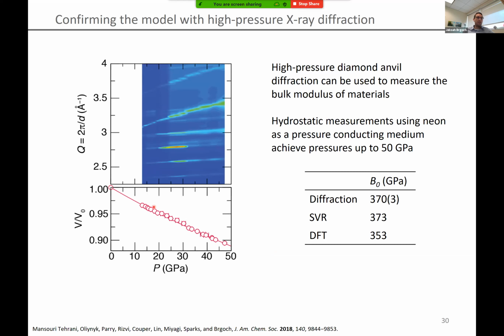You can fit the refined volume of the unit cell to a Birch-Murnaghan third order equation of state. Here by diffraction, you can see our bulk modulus is 370 gigapascals. Support vector regression predicted 373, and DFT on an ordered supercell model is 353.